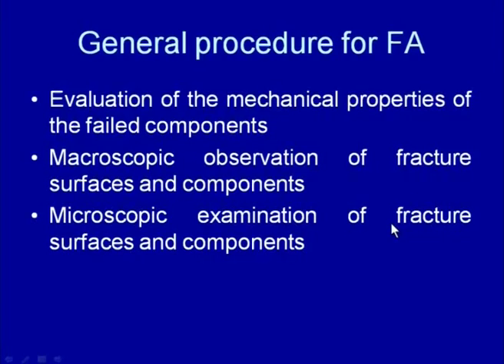So the presence of cleavage facets on the fracture surface, through microscopic examination, will indicate brittle fracture, and the intergranular fracture will be represented by the complete grain morphology present on the fracture surface, which can be observed under the microscope, indicating intergranular fracture. So both cleavage facets and intergranular fracture indicate brittle fracture, while the presence of dimples on the fracture surface indicates ductile fracture.